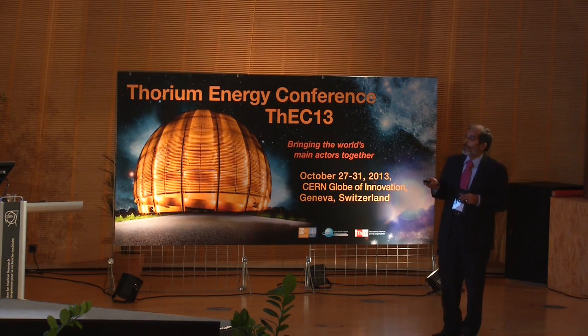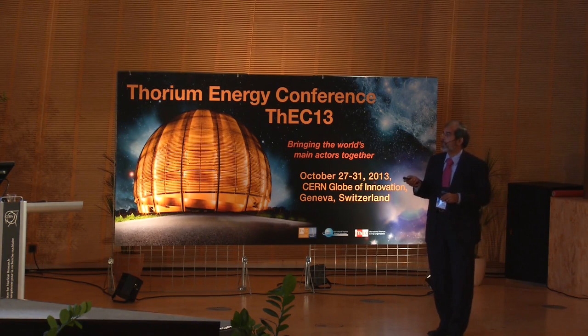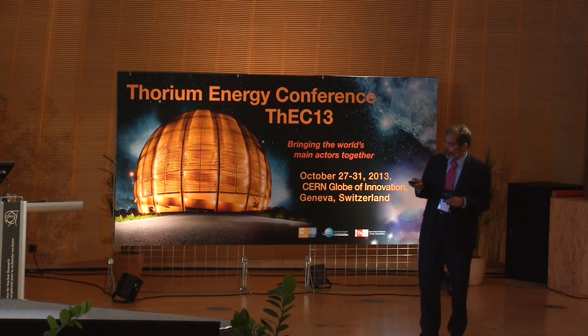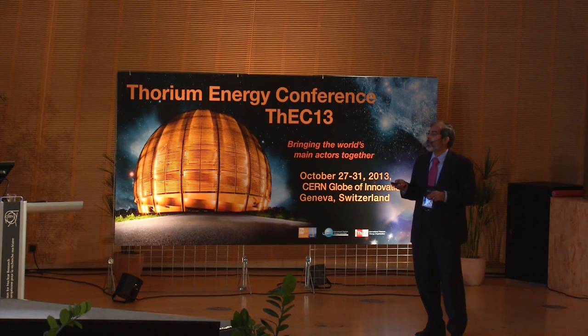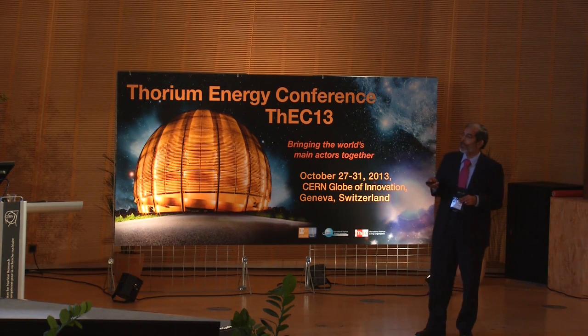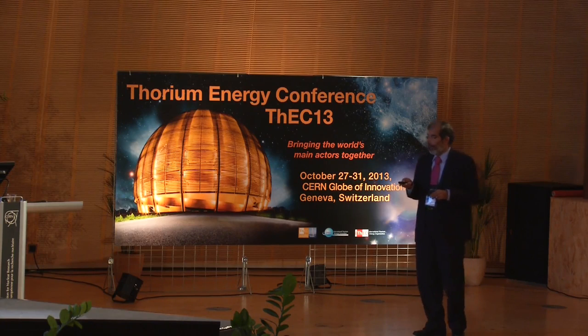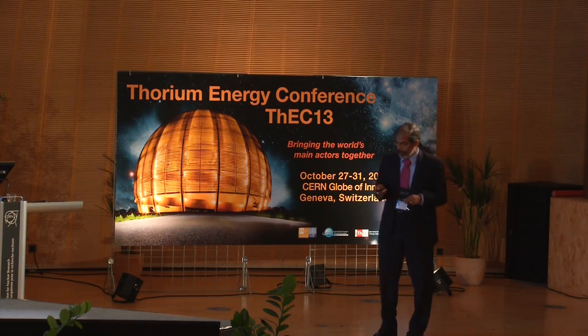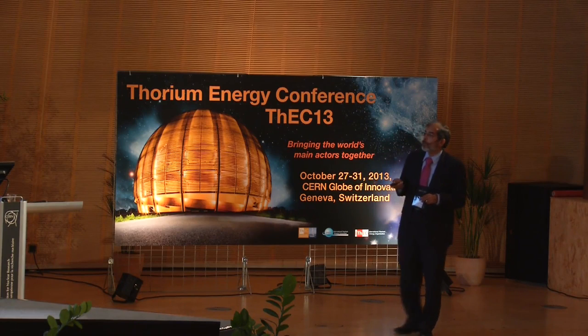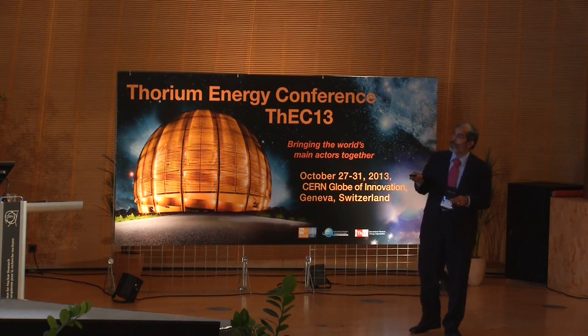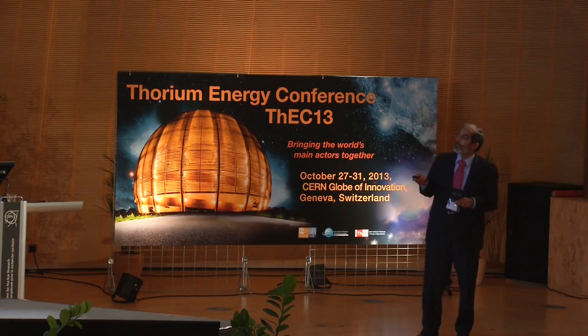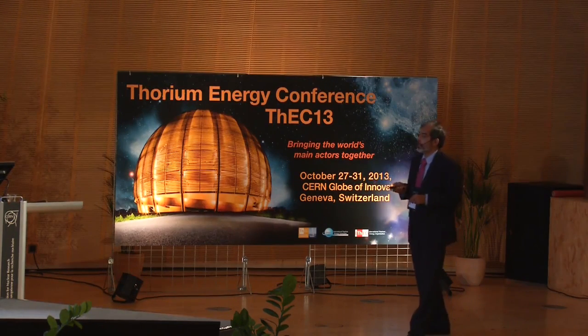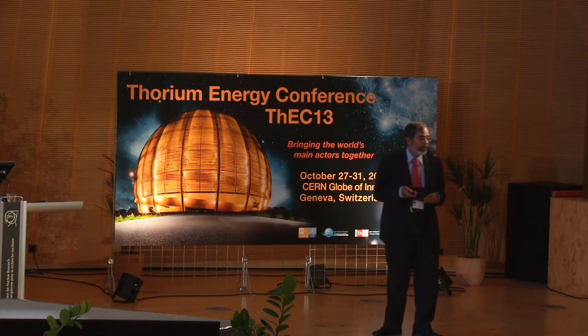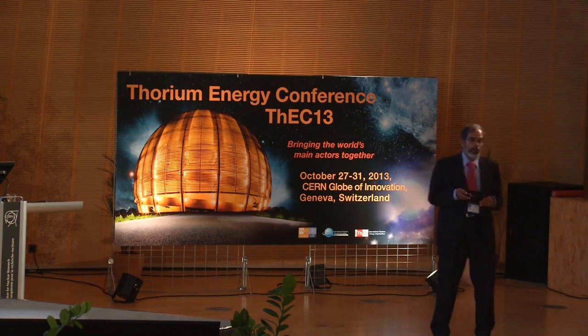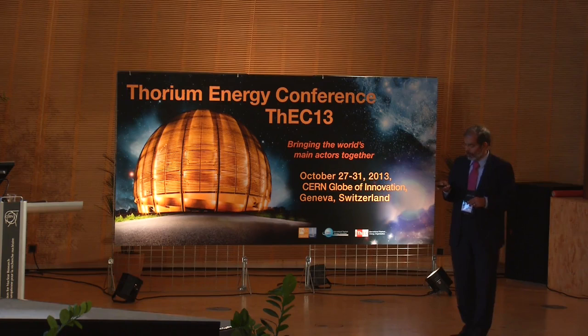We also use this niobium 1% zirconium as a structural material, and the material has been developed. And a few thermal hydraulic test facilities for code development and validation have been established. One of them is, of course, this liquid metal loop, which has been operational since 2009, and it can operate up to 550 degrees centigrade. There is another one which can operate at 1000 degrees centigrade. It has just been established.